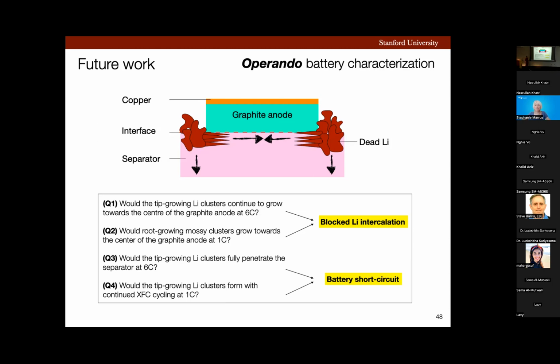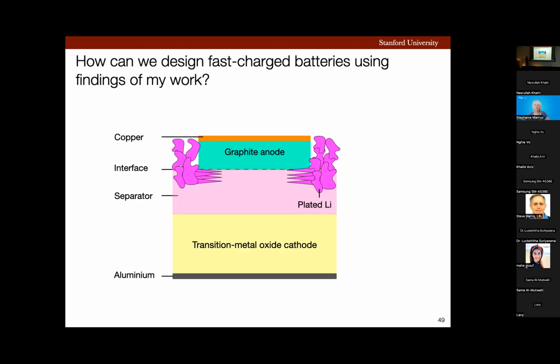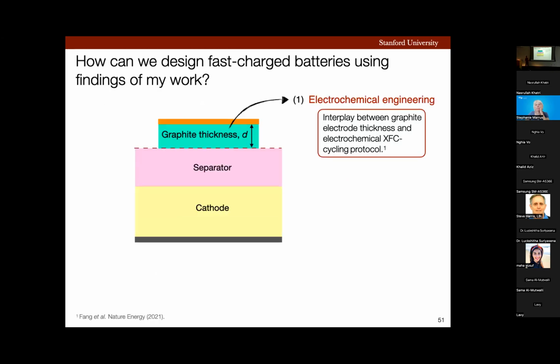But it's important to do so operando while the battery is cycling. And now the question is that, given the data that I have shown today and the information we have available, how can we design a fast charge battery? My work has shown that lithium plates at these regions where some of it is active and reintercalates into the graphite, and some of it becomes dead. Now, the first idea that I have is, can we explore the interplay between graphite electrode thickness and the optimal XFC cycling protocol, especially when our colleagues from the Stanford Material Science Department have recently shown that dead lithium can be brought back from dead.